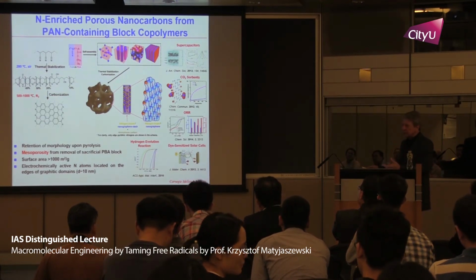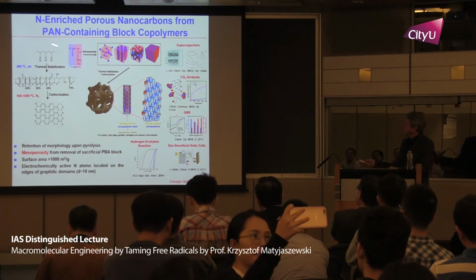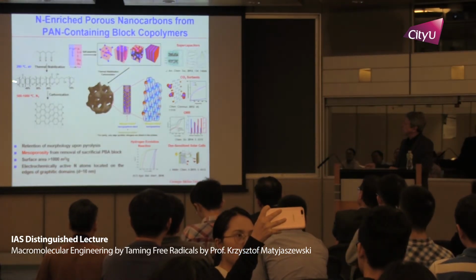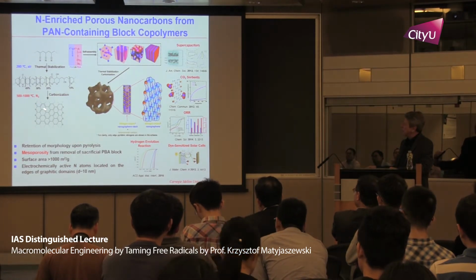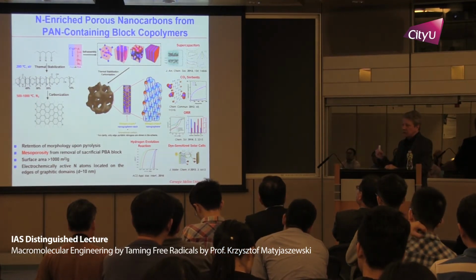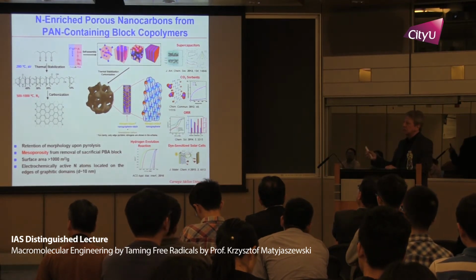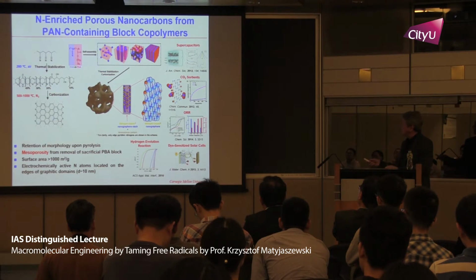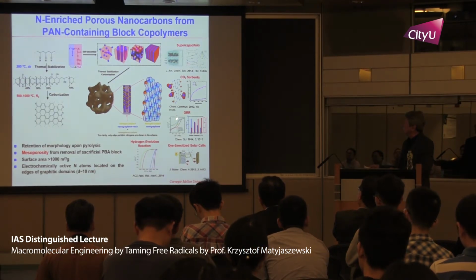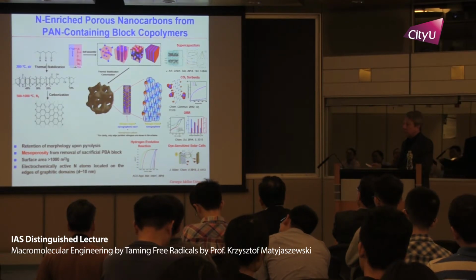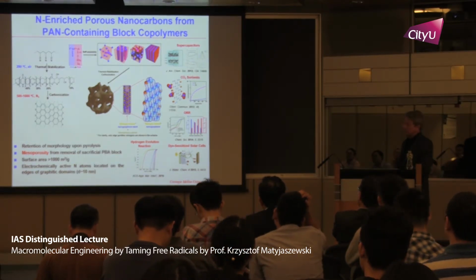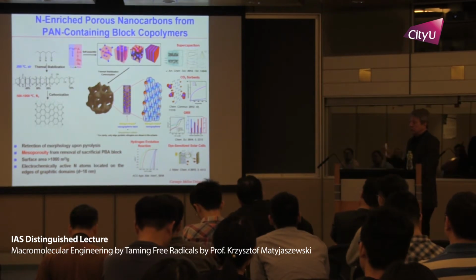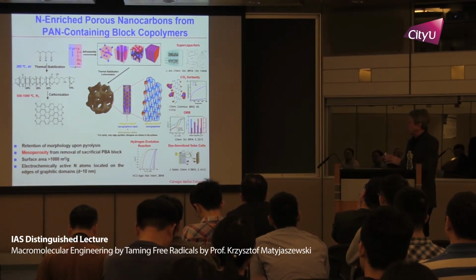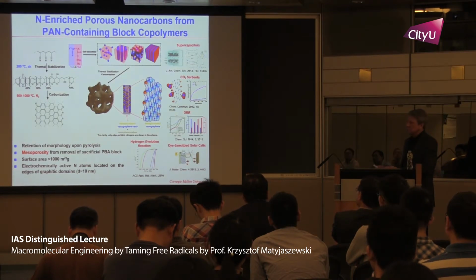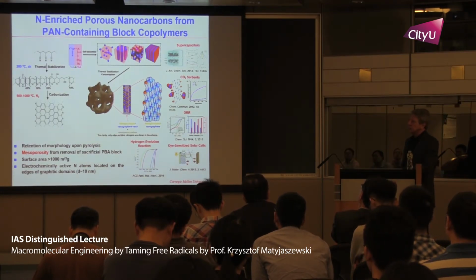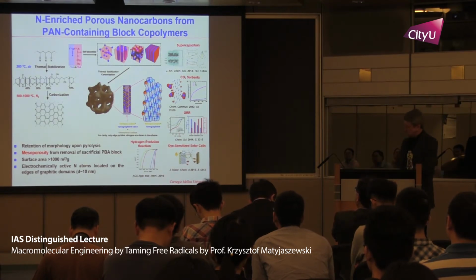So classical chemistry, which is used in carbon fibers: you start with polyacrylonitrile, then in the presence of air, you stabilize it, and then graphitize it up to maybe 800 degrees. If you go to higher temperature, you lose nitrogen. And we need nitrogen for, for example, electrocatalysis, for oxygen reduction, for hydrogen evolution, for supercapacitors, or even for carbon dioxide reversible absorption. So this can be done in a very efficient way, also doping with nitrogen up to 12%, sometimes 14% nitrogen. Sometimes with sulfur as well.